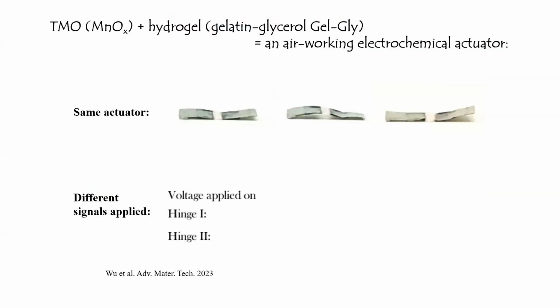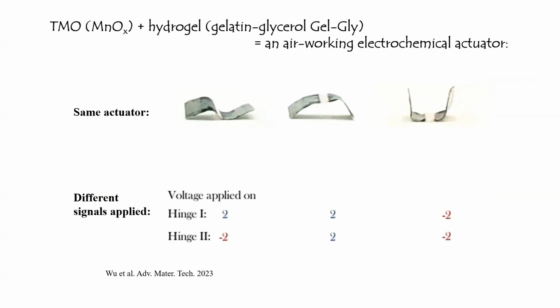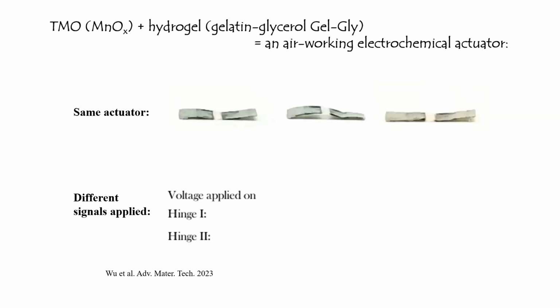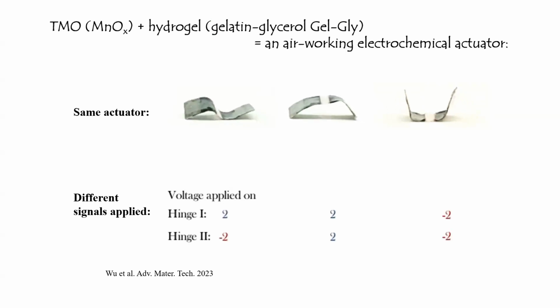And you can also use a hydrogel to be the electrolyte instead of liquid electrolyte. You can use gel to be electrolyte. So in this case, the TMO is the manganese oxide, and then the hydrogel is gelatin glycerol. So we have now made two actuating hinges here, and they are separately connected electrically. So that's why you can supply different signals to the two hinges, and then the actuator will give you different shapes.